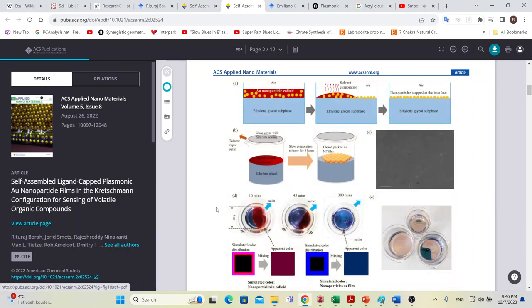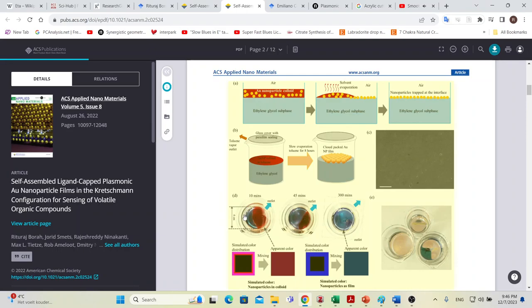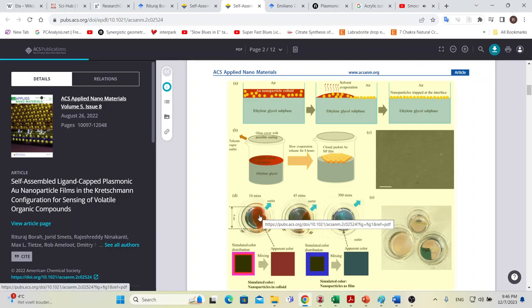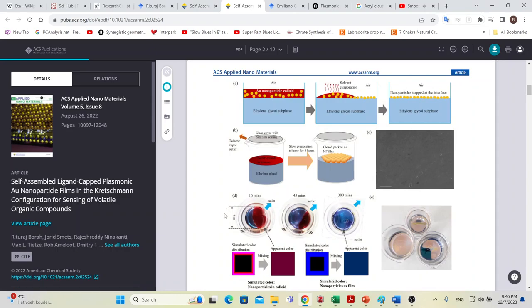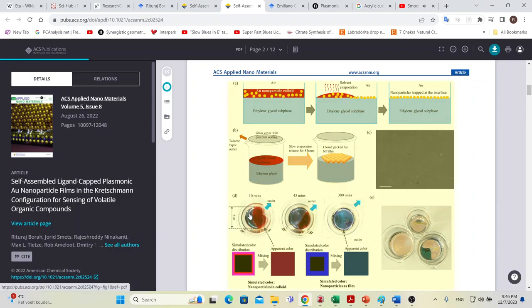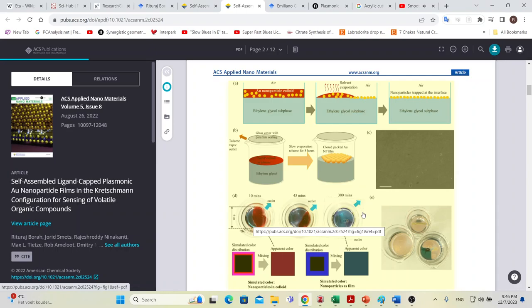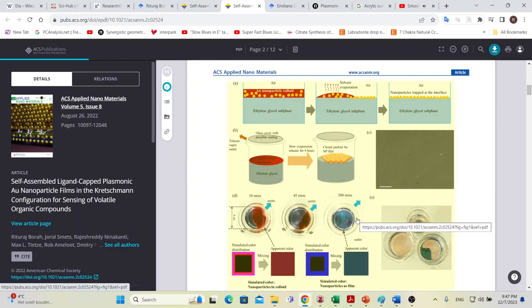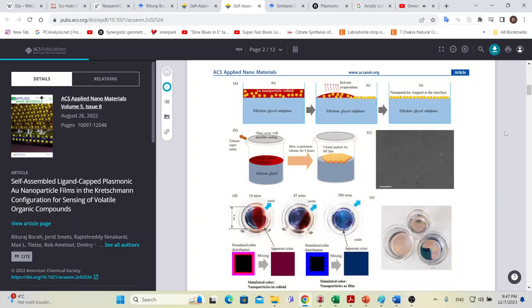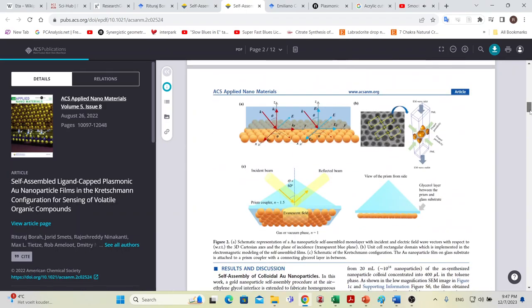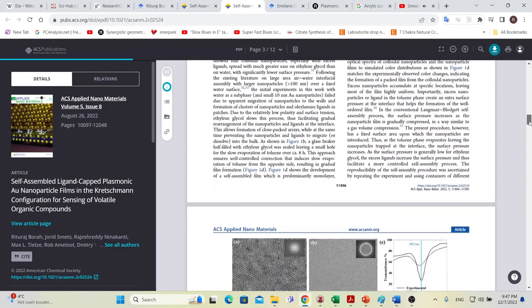If you look at the development here, gold nanoparticles are kind of floating over ethylene glycol surface and the nanoparticles are dispersed in toluene. When the toluene is drying up, you can see from one side the film is developing—the blue color is the film. After a few hours when the entire toluene solvent dries up, then we have this kind of blue-colored film.